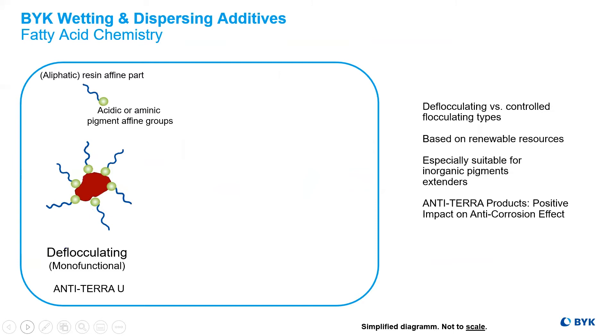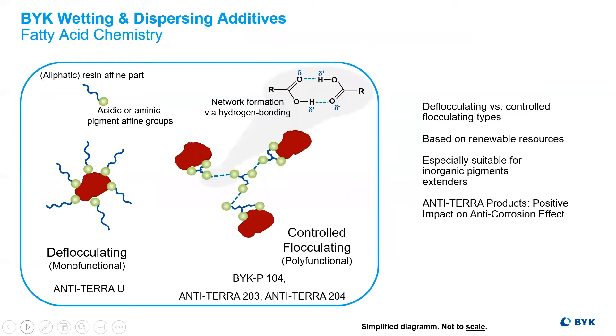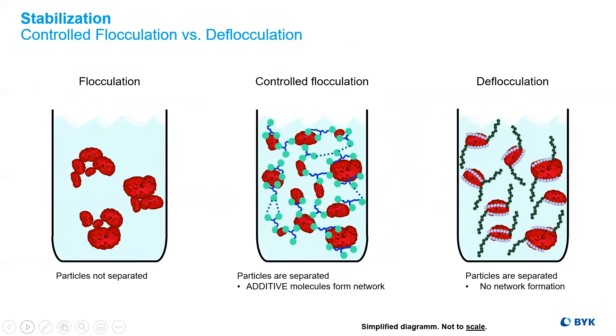They can be monofunctional with a pigment-affinitive group and a lipophilic portion for steric stabilization, or they can be polyfunctional with hydrogen bonding formation to provide a network of controlled flocculation. It really is based on the stabilization choice of the formulator.